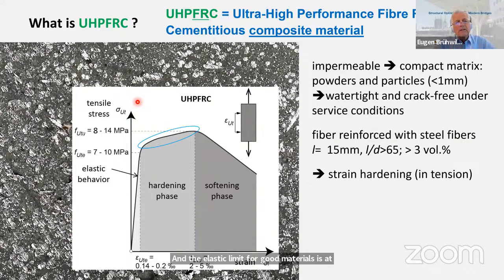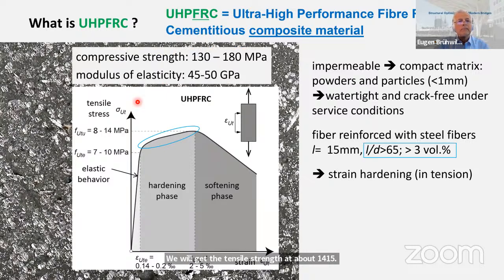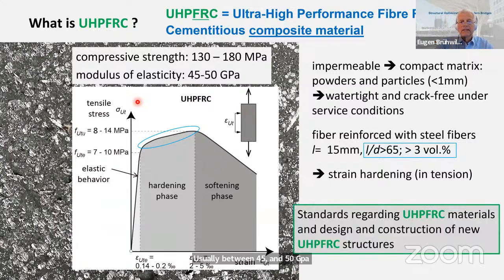And then after the strain hardening behavior, we will get the tensile strength at about 14, 15 megapascal. The compressive strength of this material is around 150 MPa, and the modulus of elasticity is usually between 45 and 50 GPa. We have standards worldwide, in particular a standard in Switzerland that I use often.